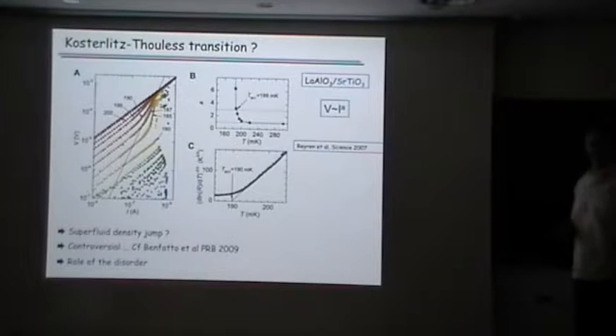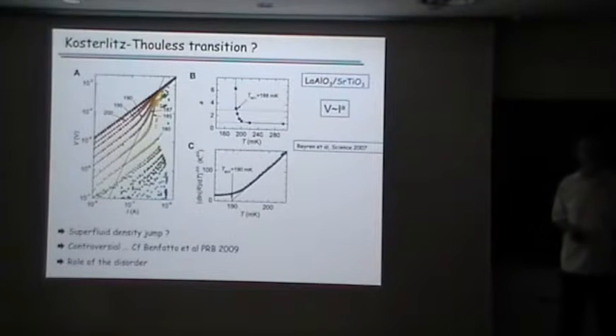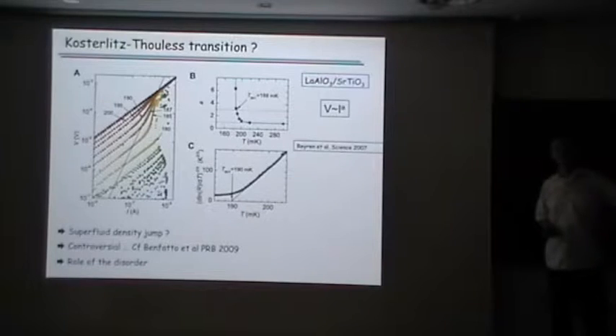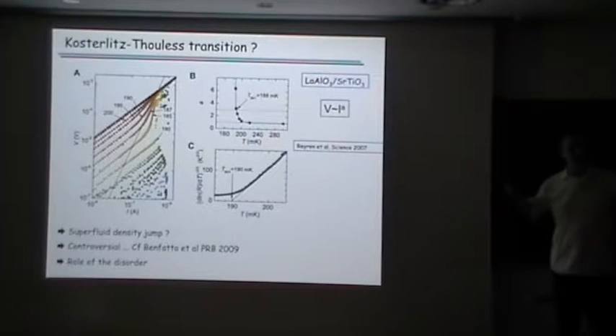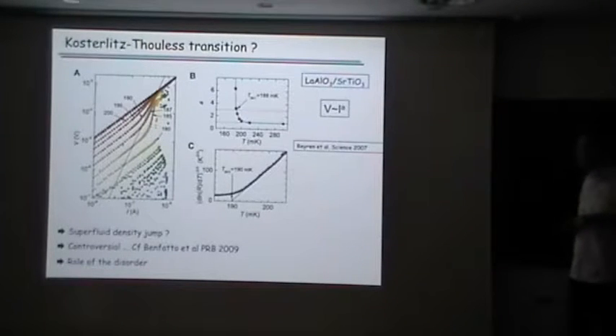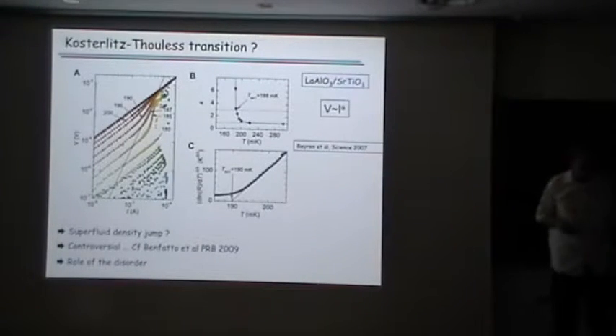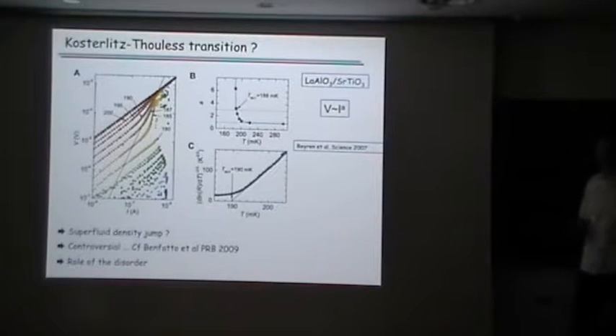If you go into details, it doesn't work that well, especially if you look at the maximum, there is a length scale, which is the size of the sample in the Kosterlitz-Thouless transition for the vortex and anti-vortex unbinding. And I mean, these numbers in the experiment don't work at all. It's not at all the size of the sample. So I think this result is quite controversial. And there is a paper by Benfatto, for instance, which explains that maybe you can understand those results just in terms of disorder.